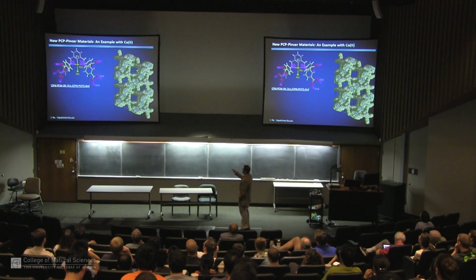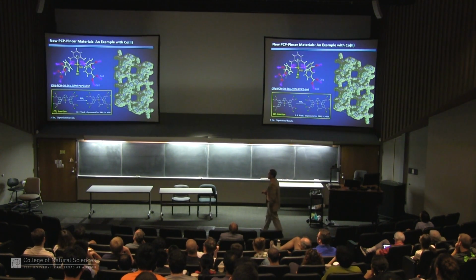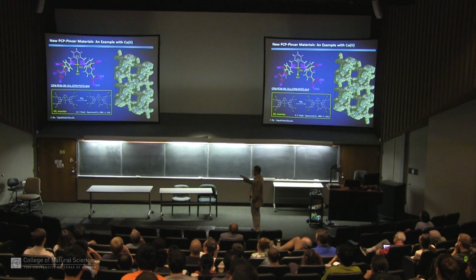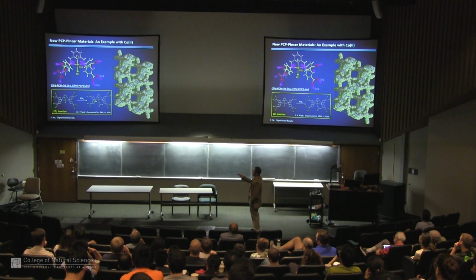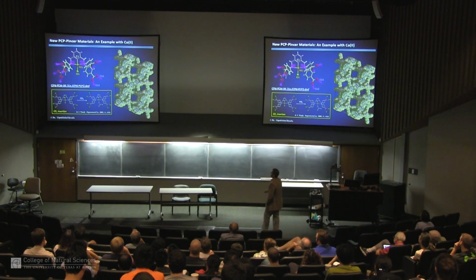You can see we've got these nice pore windows in the material. We've got access to these species built into a 3D crystalline polymer. And some of the reactions of interest, well, this PCP is known to insert CO2 into metal carbon bonds, and so this is where the project is going in the next couple of months. We're interested to see if we can use not only the material's ability to store lots of CO2, but also to react it in situ and insert into simple bonds so that we can use CO2 for useful chemistry and maybe make these